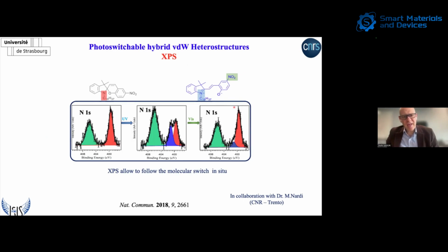Why? Well, we focus on the N1S peak. As you can notice here, in the spiral the nitrogen is in its neutral form, and therefore upon irradiation with UV light we create a merocyanine where the nitrogen is positively charged, which is accompanied by the appearance of this blue peak that can be ascribed to the positively charged nitrogen. It vanishes to a great extent upon visible light illumination, when we go back to the spiral form in which the nitrogen is neutral. Now, we can monitor these two states by scanning tunneling microscopy.